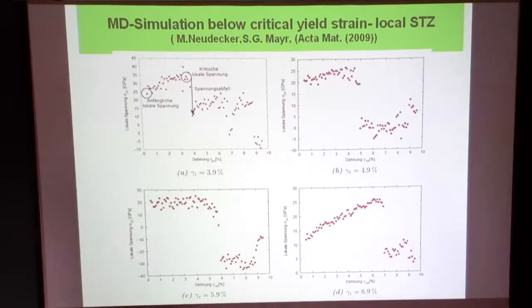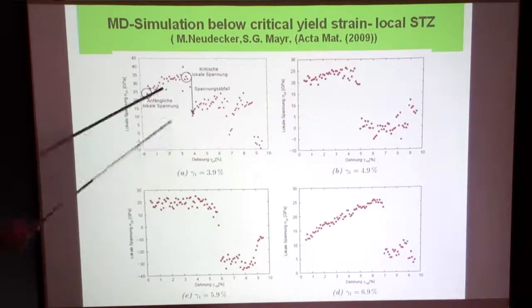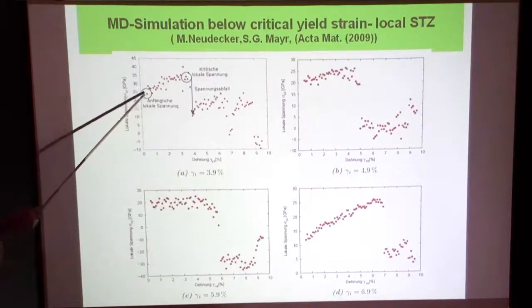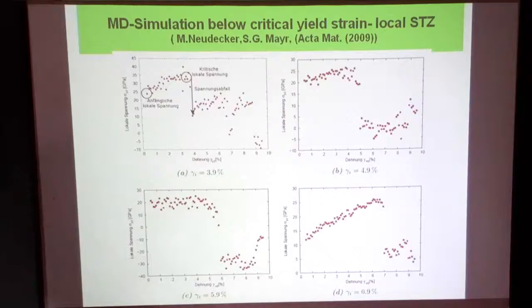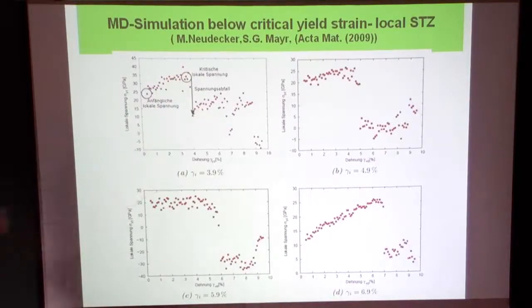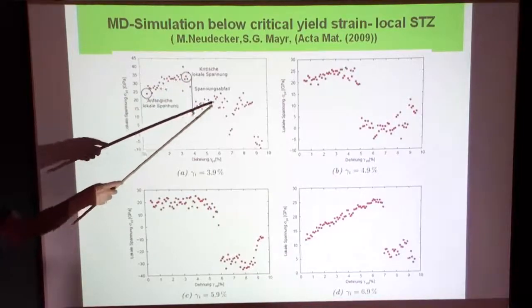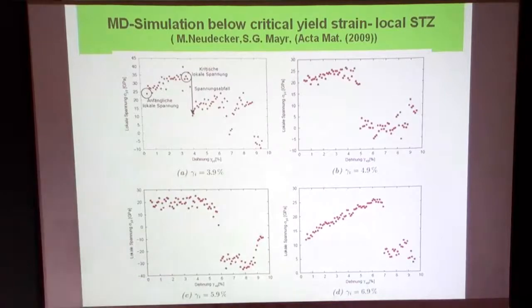But this is not a creep thing, is it? That's not the creep thing. It's just a fixed strain, and then it's different, at finite temperature, and you see the numbers are very high. I don't think the numbers are really important here. It's more or less that there is some kind of a stress drop locally inside this matrix, as we saw before. Now, what we're doing right now is looking for the motifs which are prior to the jump and after the jump. You ask what is actually going on locally: the motifs which we form under stress locally, and then see how they change after the stress drop.